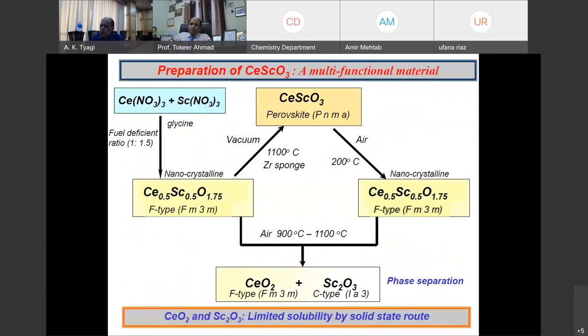I move forward to one more excellent compound, CeScO3. This compound also does not exist in the phase diagram for a simple reason, because cerium is in 3+ state. So how do we do that? Make a combustion reaction, take glycine as the fuel, you get a precursor. You get a compound which the phase diagram might expect. You get Ce0.5Sc0.5O1.75. At a glance, you know, as a chemist, if you knock out 0.25 oxygen from here, you get CeScO3. So from fluorite, you get perovskite; oxidize, you get fluorite.